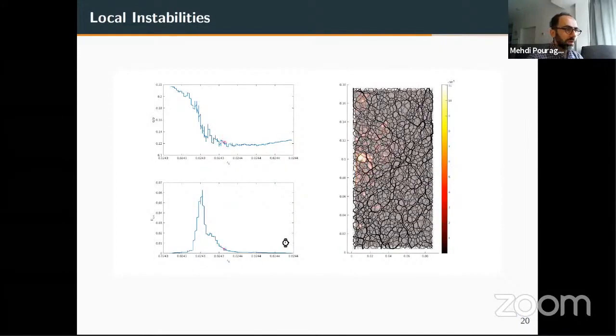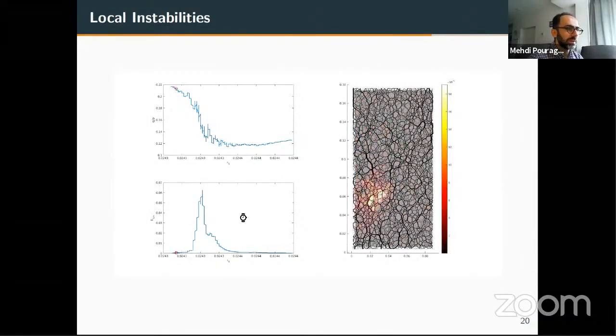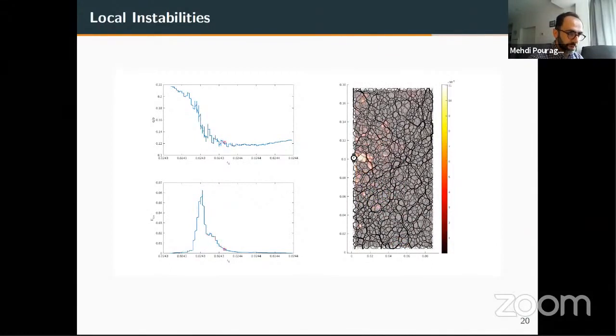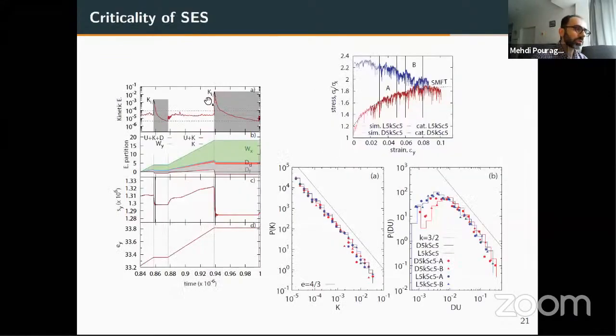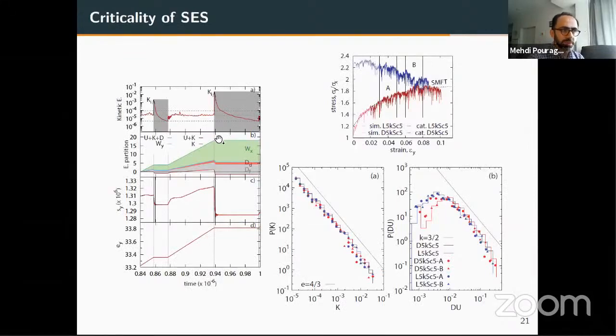Here is a movie that shows one of the drops in the stress ratio, and this is the increase in the global kinetic energy, and this is the field of the kinetic energy that you are seeing here. You see lots of activity here. As the stress drops, you get a peak in the kinetic energy, and a micro avalanche happens in this range. I'll let it run once more. You see the event is happening here, then it dies out and goes back to the background level. So we managed to separate all these micro avalanches. This is mostly done by Jordi.